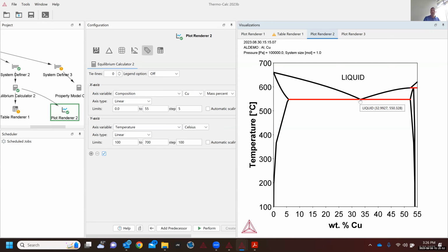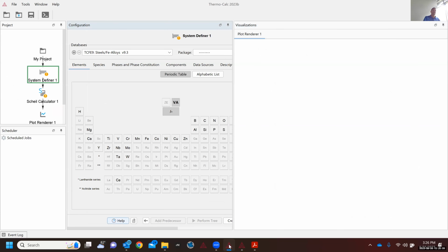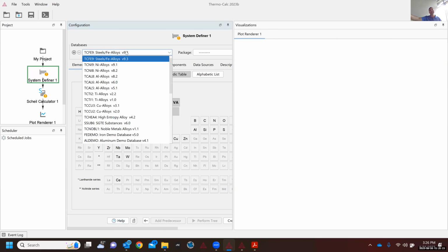And so that's a feature of the Scheil solidification. Everything is going to slide down until it reaches the point at which liquid is no longer stable in the entire equilibrium phase diagram. And so that last little bit will form as eutectic. Is that realistic? Well, it depends on exactly what you need. The composition curve is going to be quite good. When you get out to the last little bit to solidify, you start to get a lot of solute enrichment in the liquid.